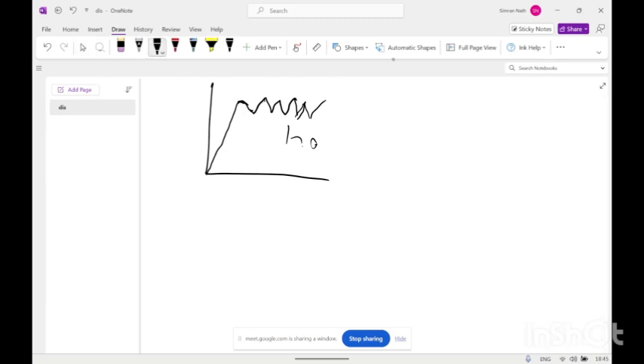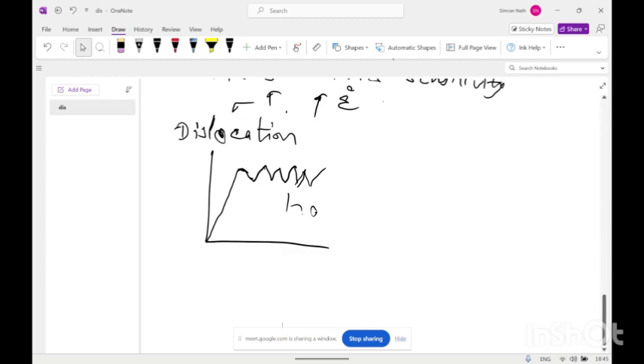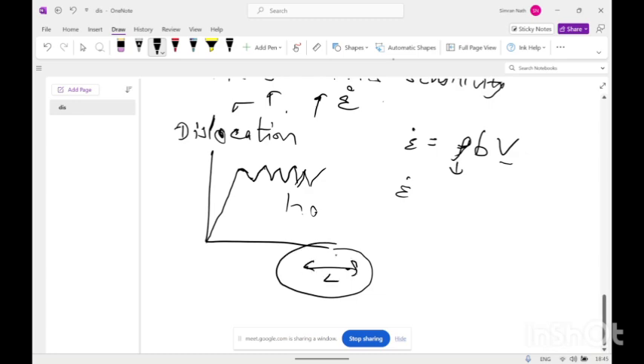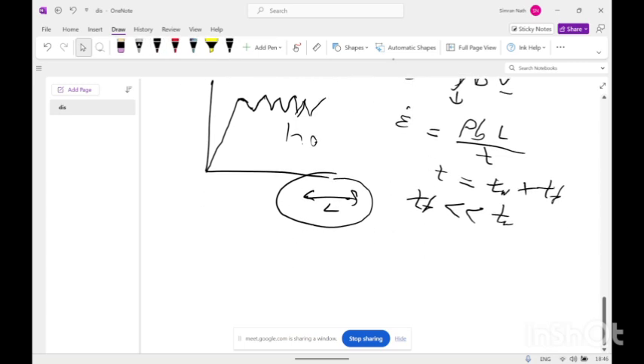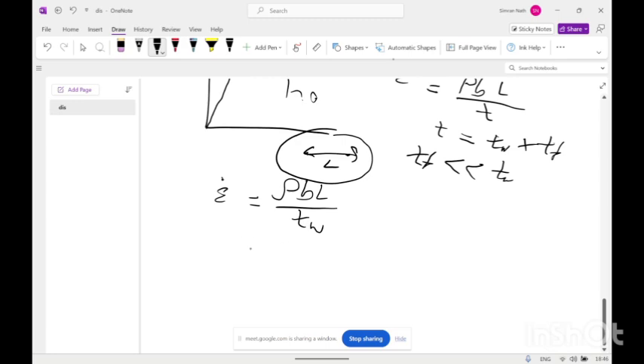So how is time related to the strain rate? The strain rate can be written as rho b v. Rho is the dislocation density, b is the Burgers vector, and v is the velocity. For two locations in the material, if the distance is L, the velocity will be L by t, so strain rate is rho b L by t. Here t is the waiting time of the dislocation plus flying time. The flying time is very small compared to the waiting time, so the equation can be written as rho b L by t w. So if the waiting time is less, that means the strain rate is high.